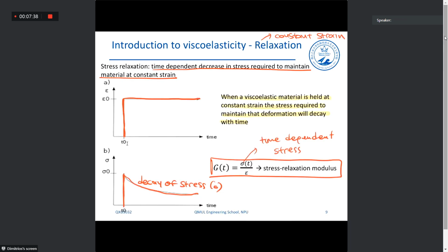And here, in terms of stress relaxation, we have a constant strain, and I told you we measure the amount of stress, the decrease of stress that is required to maintain the strain constant. Okay, and there is a decrease of stress, as we can see in this graph, in an attempt to keep the strain constant. Okay, it is impossible to keep a constant strain without a decrease of stress.